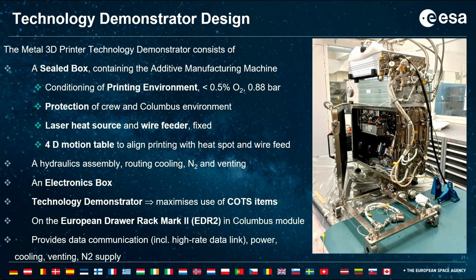Looking at the printer itself, we had a sealed box to protect the crew around it from temperatures, fumes, etc. We work with a very small content of oxygen in the atmosphere for the reason we talked about, the oxidation. And what we did is we purged the chamber with nitrogen to decrease the amount of oxygen, so below 0.5%. The pressure was quite low, 0.88 bar.